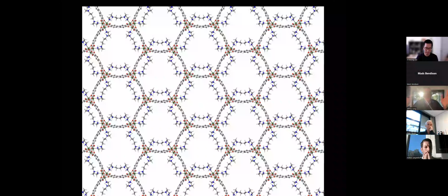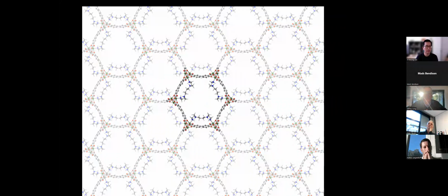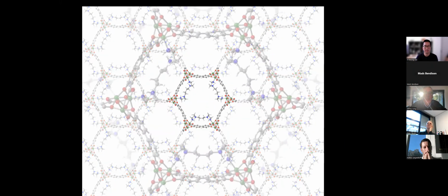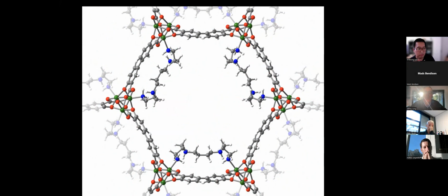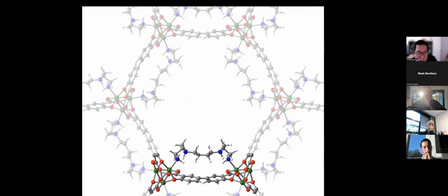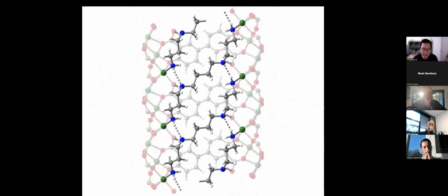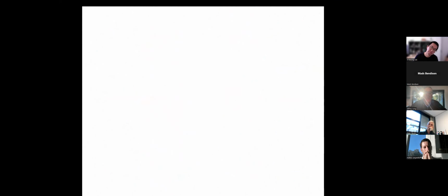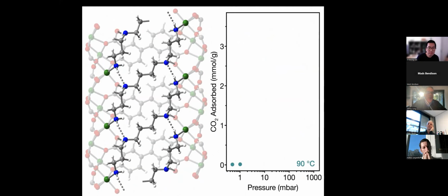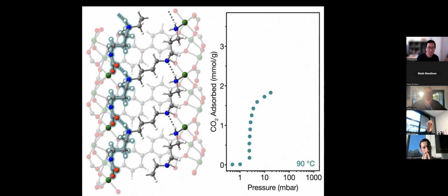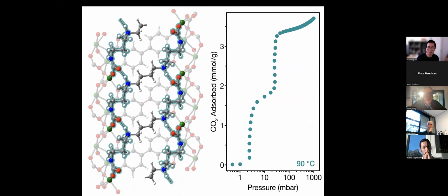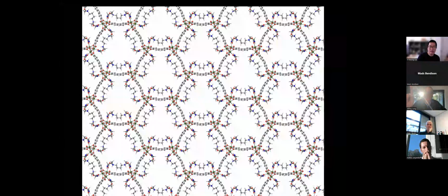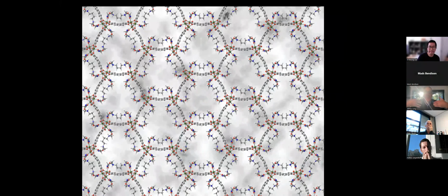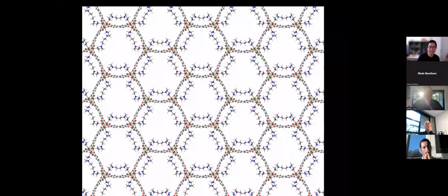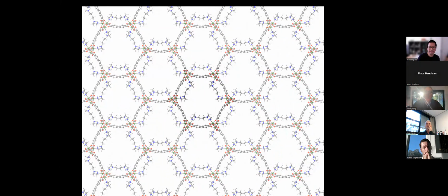So here's just a video showing you how this works. So here we're focusing in on one channel of the MOF with the tetraamines loaded, and we'll rotate 90 degrees now, looking down on the MOF, the rows of tetraamines. And it turns out there's actually slightly different thermodynamics for the first chain at one end that forms and the second that forms at the other end. So you see a double step instead of a single step. Once you've loaded with CO2, you can apply steam, release the CO2, and then you start again.